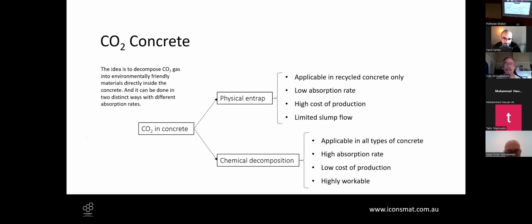Well, I'm not sure exactly what admixture you're referring to, but the use of any chemical admixture, of course, has a big role in reducing the water requirement and hence the cement requirement. And therefore, chemical admixture has been used for many, many years in reducing the cement content and therefore embodied carbon. Now, with this range of natural admixtures, I am not sure whether it works in a similar way or not. But if it helps to reduce the water requirement, then the concept that we understand from the use of chemical admixture would apply.